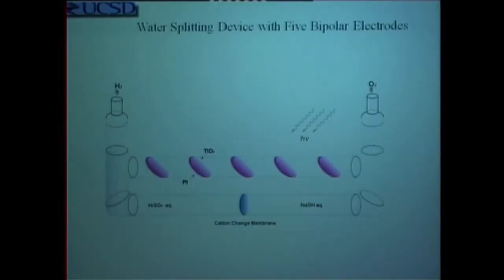We also have been able recently to generate a water splitting device so that the additive potential that one gets across this array, whether it's supported on glass or a plastic surface, allows you to develop enough potential so that you can do that experiment entirely without an electrical cell. You can do it just by the absorption of light. Because with five cells of this sort, there's enough potential that the light absorption can affect water splitting.